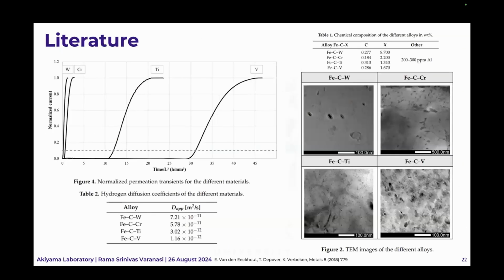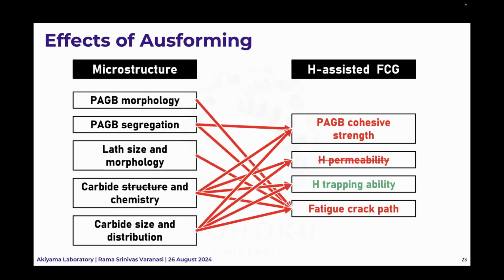For example, if you look at literature, of course, this is for different alloying elements. We see very clearly that in some cases, some carbides very drastically shift the breakthrough time and change the diffusivity. So in our case, we can safely assume that the effect of Ausforming on the hydrogen permeability is negligible. We are yet to perform hydrogen TDS studies to look at hydrogen trapping ability.